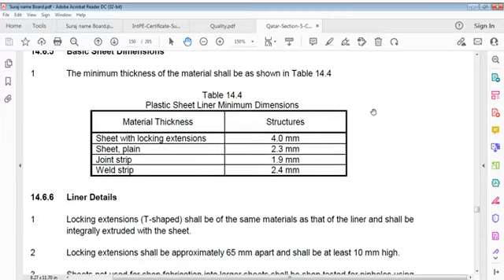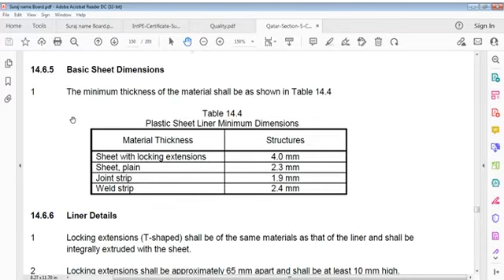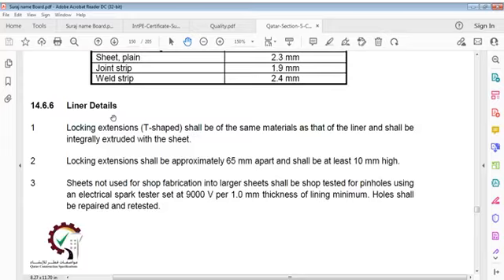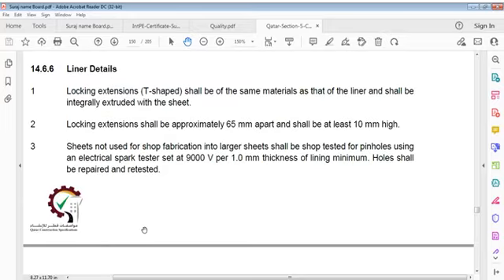Basic sheet dimensions. Minimum thickness of material shall be as shown below, and that is plastic sheet minimum dimensions. Material thickness, that is sheet with locking extensions, 4 mm. Sheet plain 2.3 mm. Then joint strip 1.9 mm. Weld strip 2.4 mm. This is basic sheet dimensions. Now liner details.